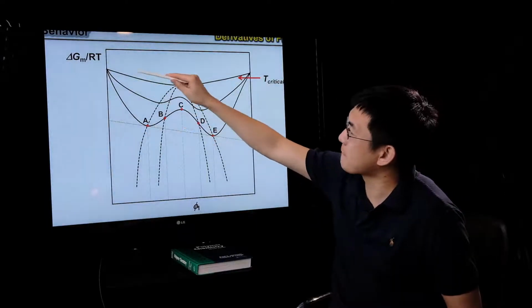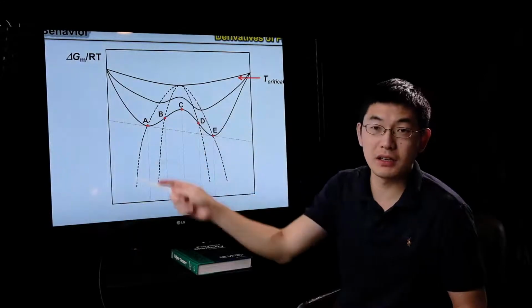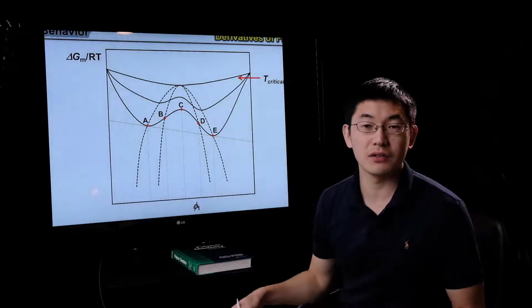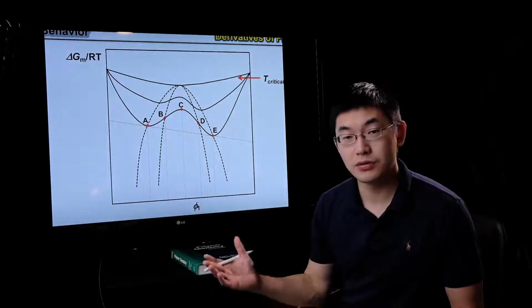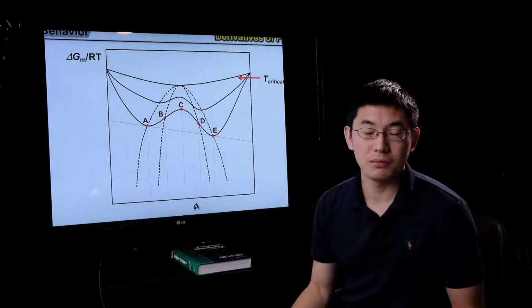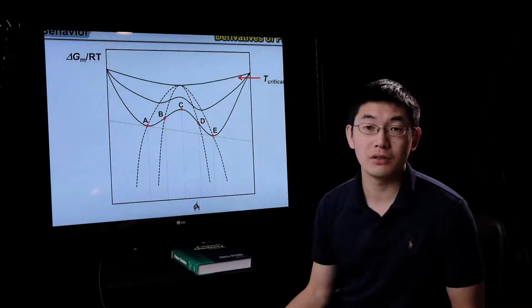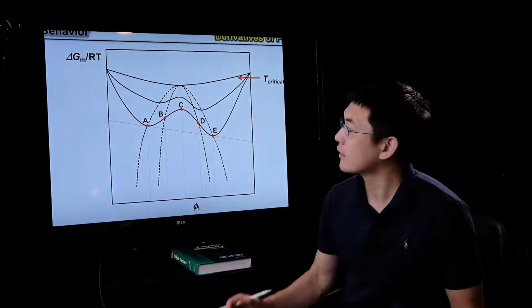Within the same solid curve, we plot 3. And the differences with respect to those 3 are just a different temperature. So if we increase or decrease the temperature, our delta G curve will be different. And you should know this because one of the parameters, delta entropy, is dependent on the temperature. So your delta G will be equal to delta H minus T delta S. So there's a temperature term there, and this will influence the shape of your delta G.